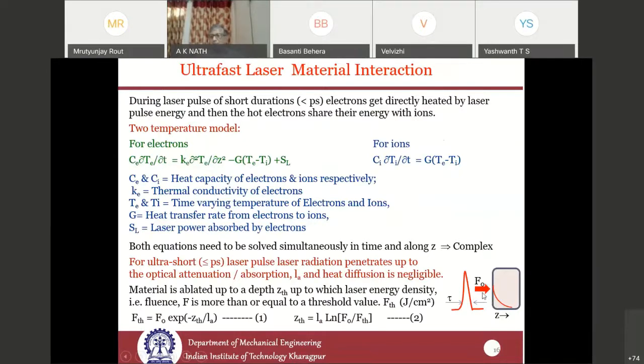Given an intensity or fluence F0 incident on the surface, one can find the threshold depth up to which the material gets ablated. This can be found from this expression — the threshold depth is where the intensity has reduced to the threshold value. By taking the log of this equation, you can find the depth up to which the material gets ablated.